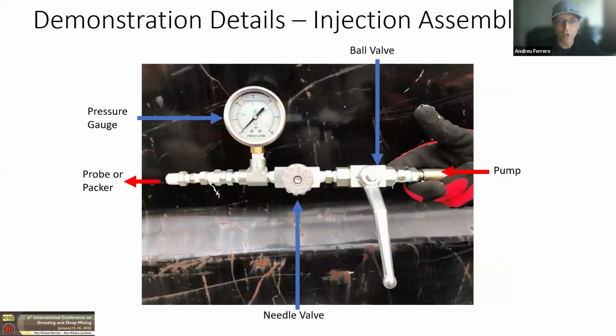This is a typical injection assembly. From the pump, the material flows to the ball valve, which acts as our on-off switch. The needle valve is what we use to control the flow rate or pressure into the system. And then the pressure gauge is what we use to monitor the back pressure on the system. So once we open those systems up, we'll have grout flowing into the soil, and then that pushes back on the pressure gauge, telling us what pressures we're exerting on that soil.